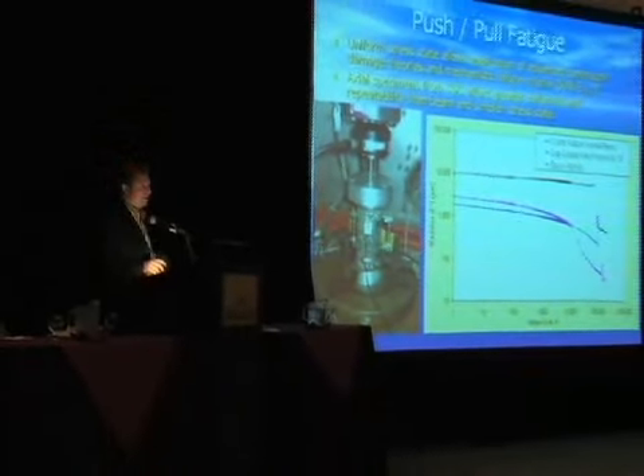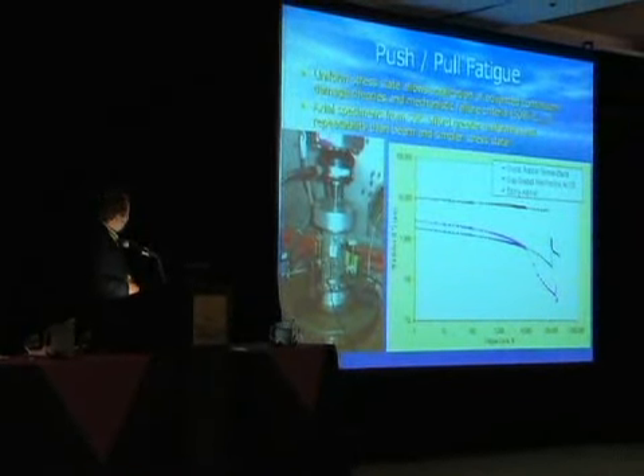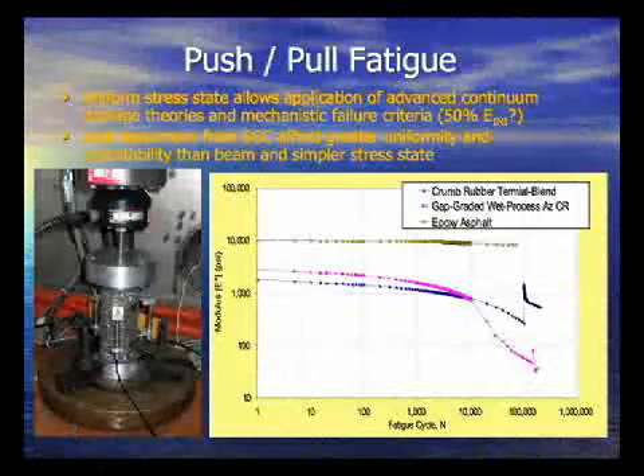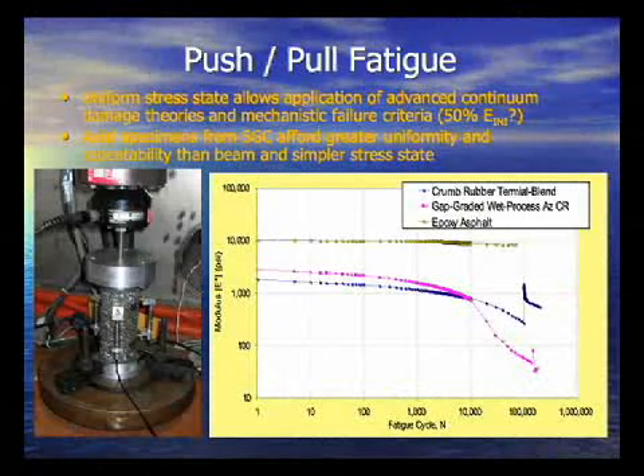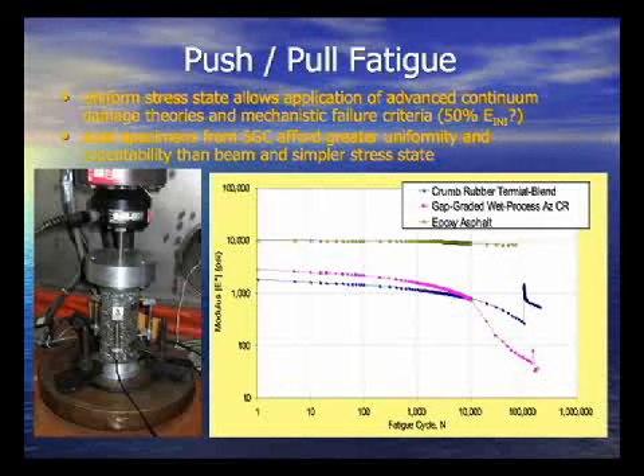And this has some benefits, and it also has some disadvantages that I'll admit to as well. Number one, it comes from the Superpave gyratory compactor, so the aggregate orientation is different. But again, we're looking at this in terms of a surrogate test, okay? Also, the stress state is axial. It's not bending like in the beam fatigue, so we're able to look at some of these continuum damage theories, which give us maybe a more mechanistic, laboratory mechanistic definition of failure.